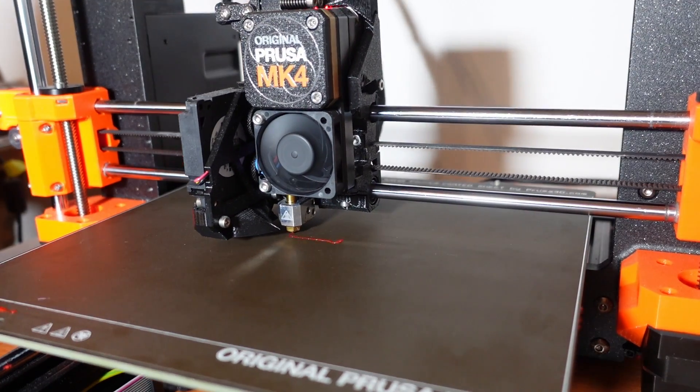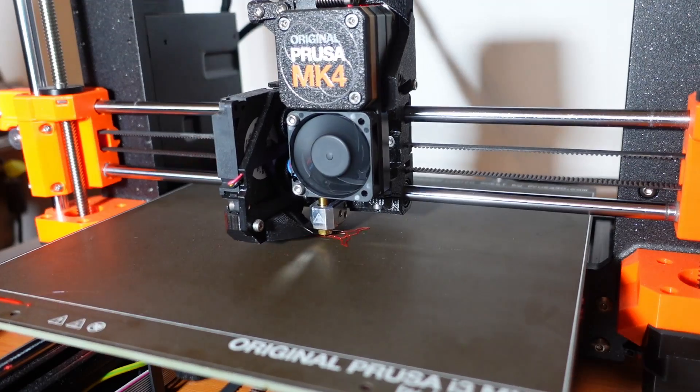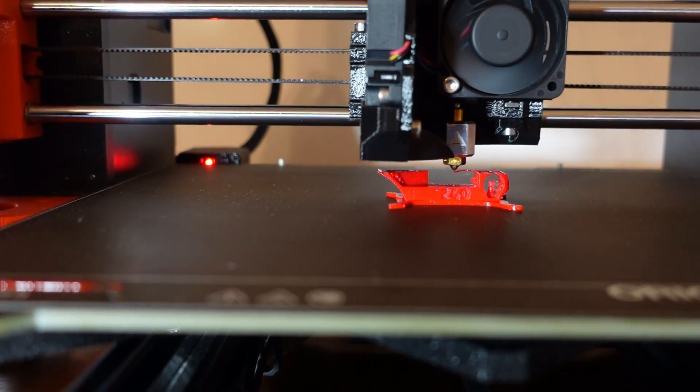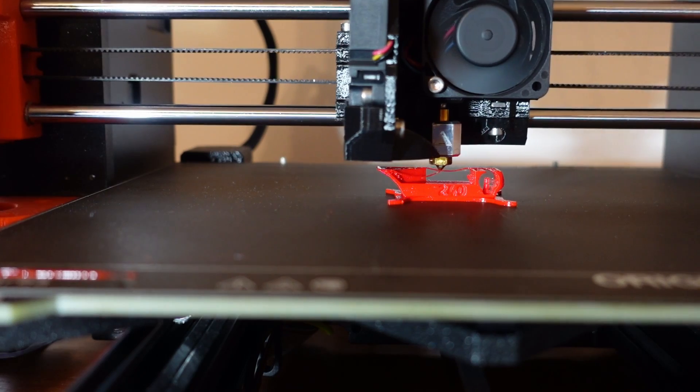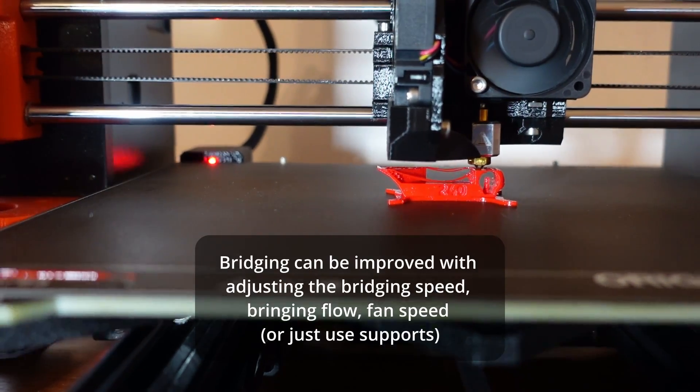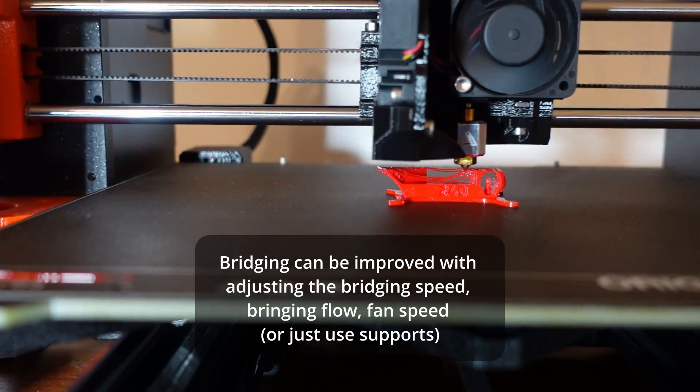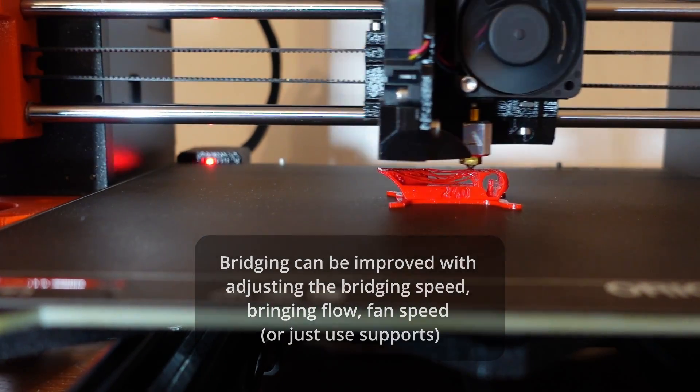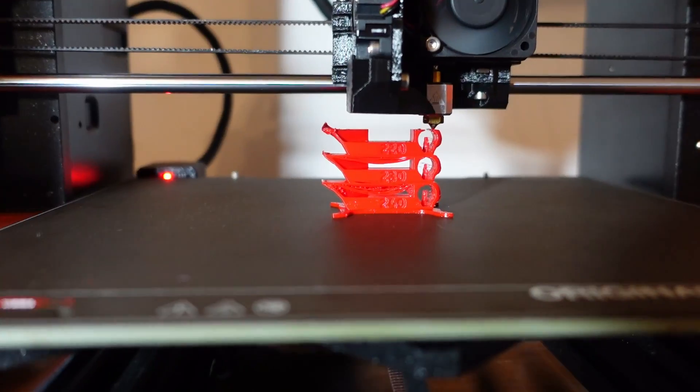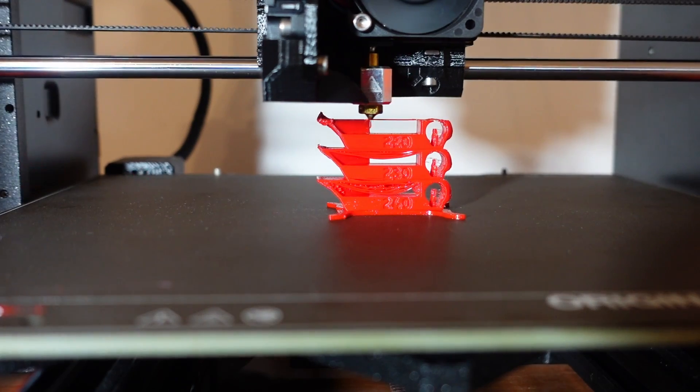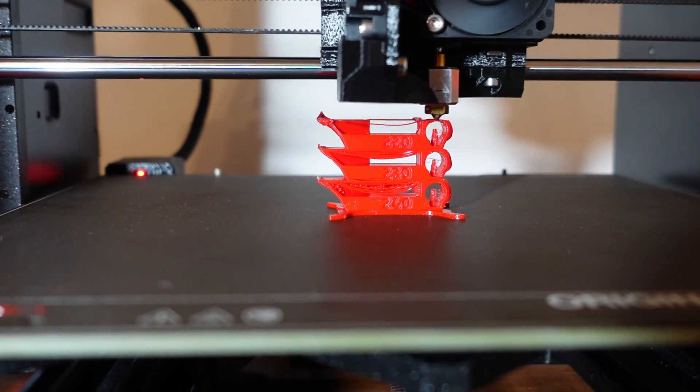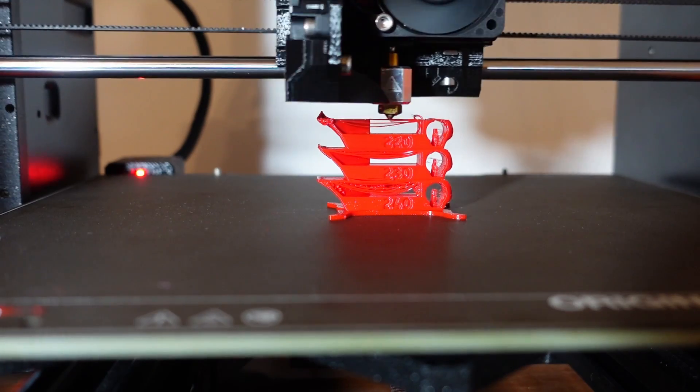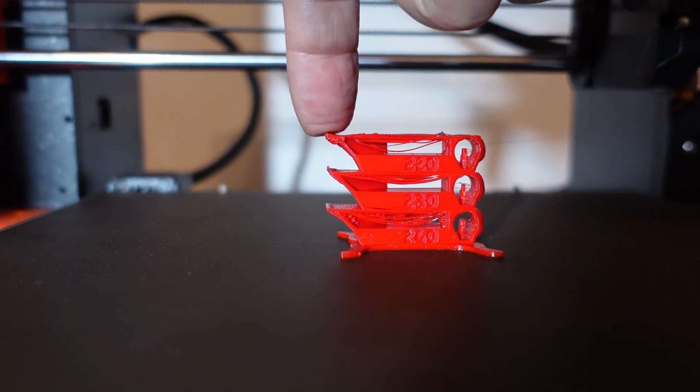This is the printing of the first layer. The adhesion is great, this is the Prusa Satin sheet, 50 degrees Celsius on the bed surface. And I know that with TPU filaments I will have a problem with bridging and this wasn't an exception. On highest temperature element, bigger bridging was failed. On 220 degrees Celsius the bridging was better, but here I faced a different problem - curling up on that bigger overhang.